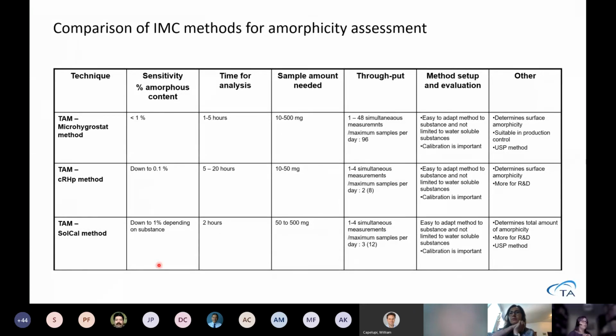The SolCal method will dissolve the whole particle, so you will see if there is an amorphous part also within the particles. So you can get the time scales, how much sample you need for the different measurements, and how many simultaneously. So the Microhygrostat, of course, is a higher throughput method as well. And both these two are USP methods as described in that. And we will see that this RHP is more for R&D to evaluate what's going on and when it's going on.